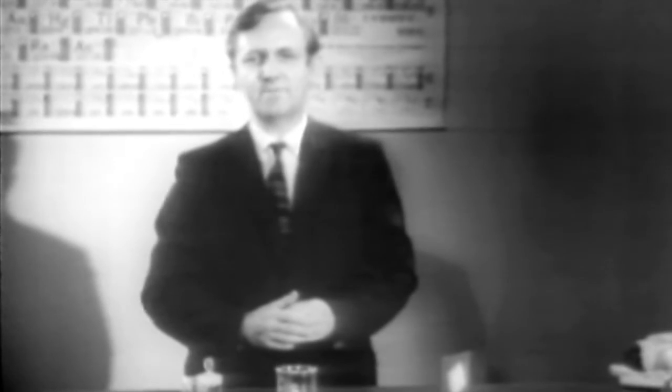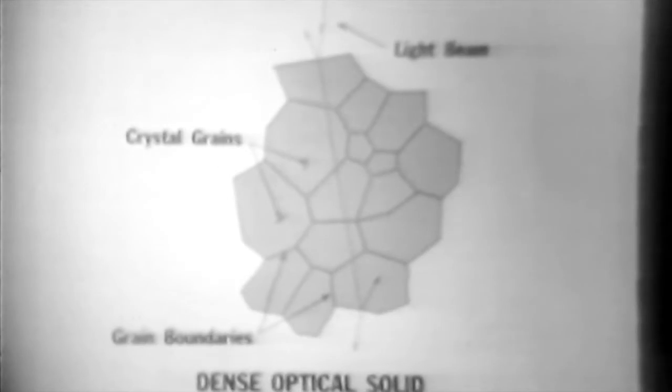There are just as many internal surfaces, but because the liquid wets the glass, these surfaces are now in close contact, and it seems that they don't scatter or reflect the incident light beam. This simple experiment would suggest that if by some means we could make a very pure, very dense ceramic in which all the grains were forced into very close contact, then the material might become transparent and transmit the light beam.